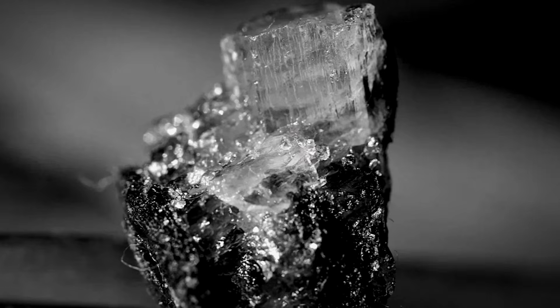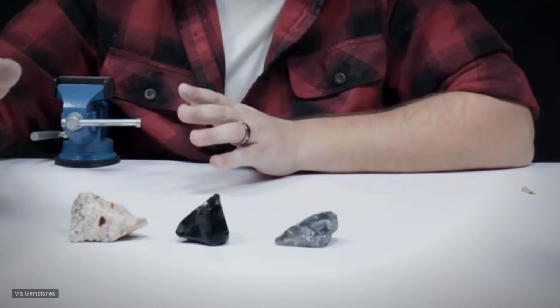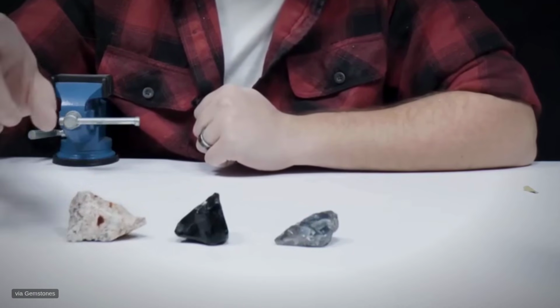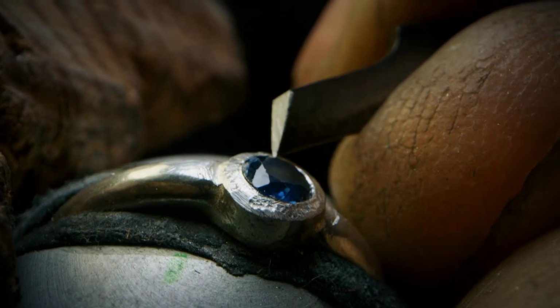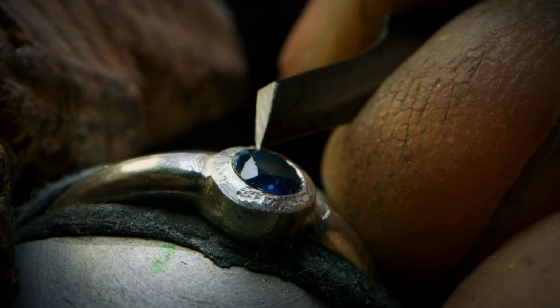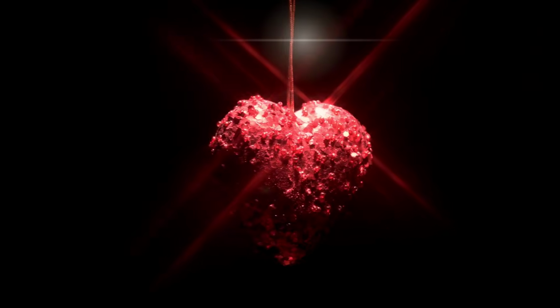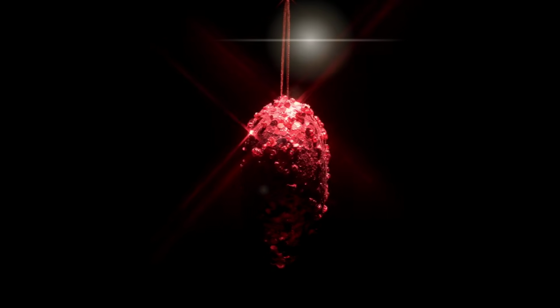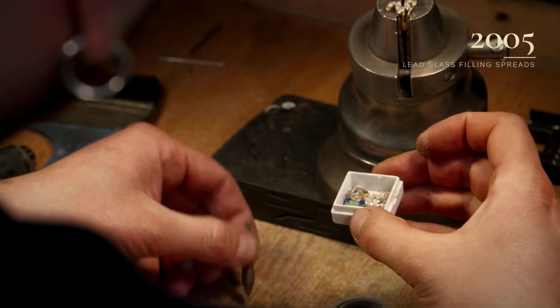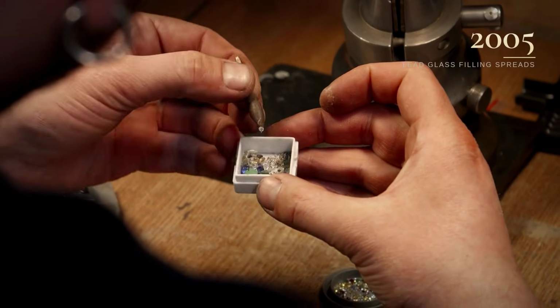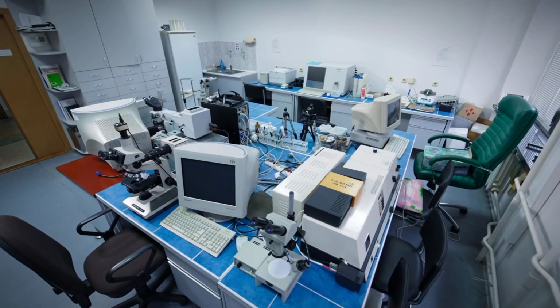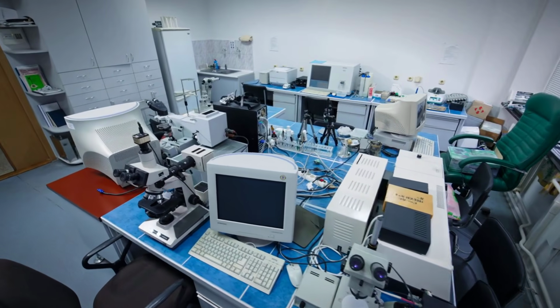Take low-grade corundum, material so fractured it is nearly unsaleable, and fill the fissures with molten lead glass. The glass has a refractive index close to ruby, so the cracks visually vanish and a cloudy broken lump becomes a clear glowing red stone. The treatment swept the industry starting around 2005, and it arrived fast enough that parts of the trade immediately asked the laboratories to flag these stones separately.